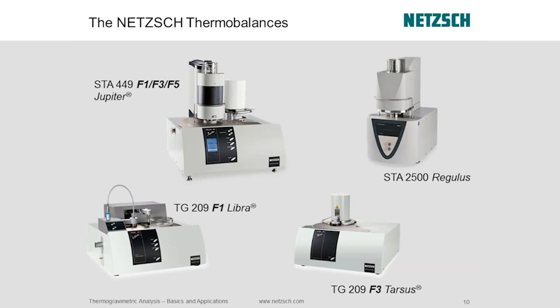You don't want gases coming in from outside the TGA and reacting with your sample, whether it's issues of sample reaction or if you're using an evolved gas analyzer to look at the composition. You really want the internal atmosphere to be as clean and pure as humanly possible. And that's achieved through a vacuum tight design. So we'll talk about that a little bit more later, but I really want to reinforce that point. NETZSCH systems are top loading and they are vacuum tight.